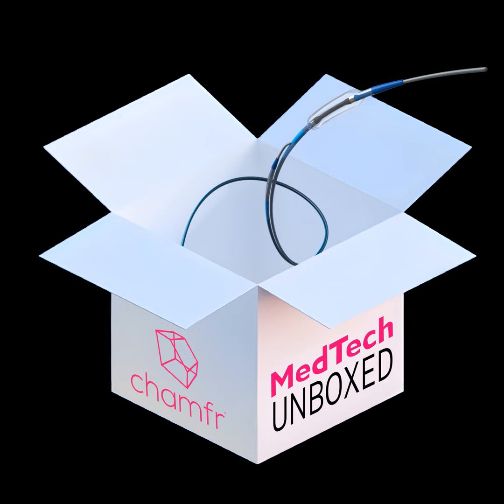We actually measure the diameter at this inflated state, and we found that the same dimensions in the tube, right, can yield two completely different blown dimensional states, depending on your temperatures, your residence time, your drawdown ratio, tank gap, all the different extrusion parameters that affect the performance of this tube. So just because you're able to hit the dimensions of the tube doesn't necessarily mean that tube is going to work for blowing a balloon.